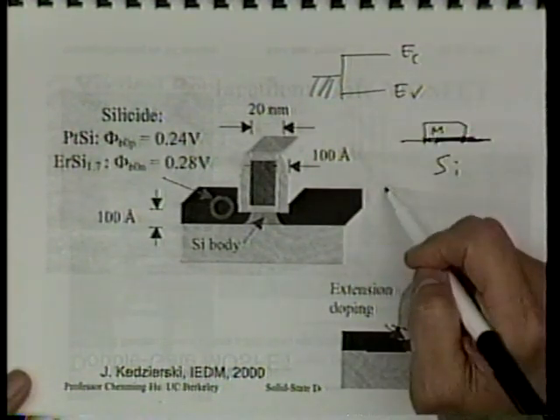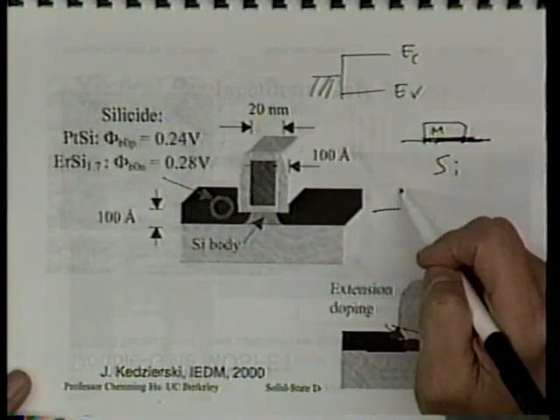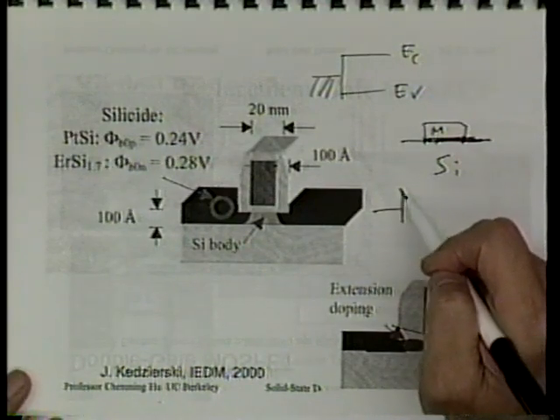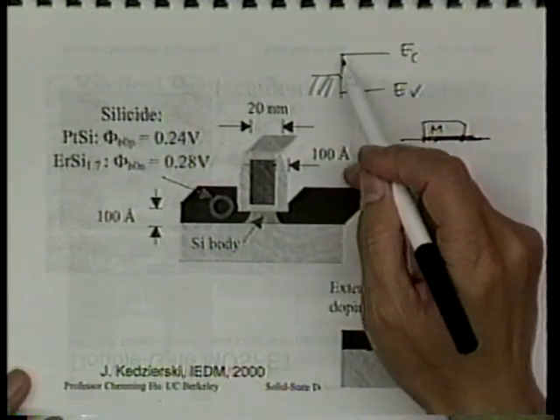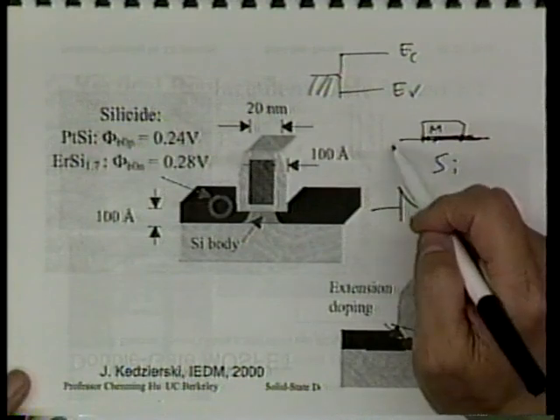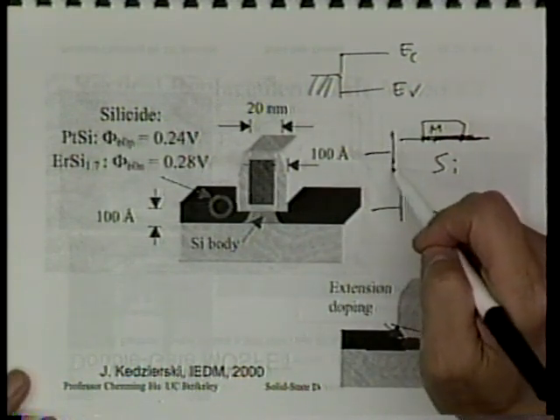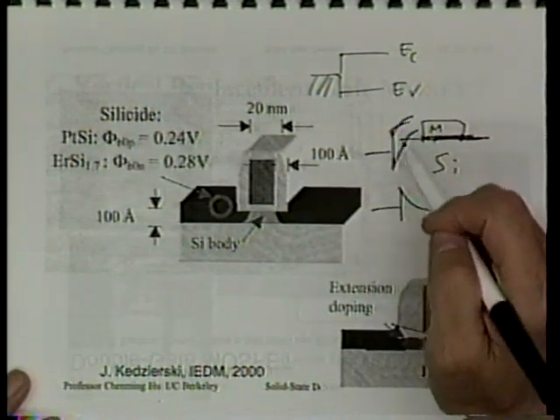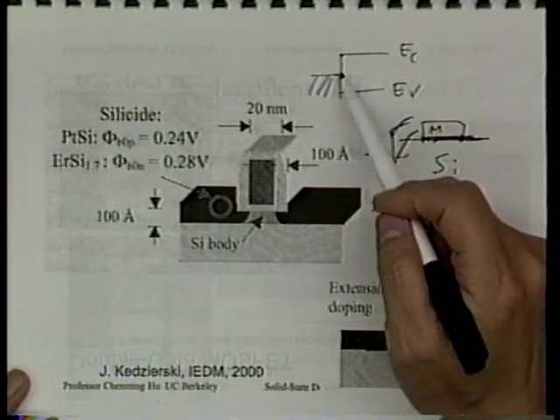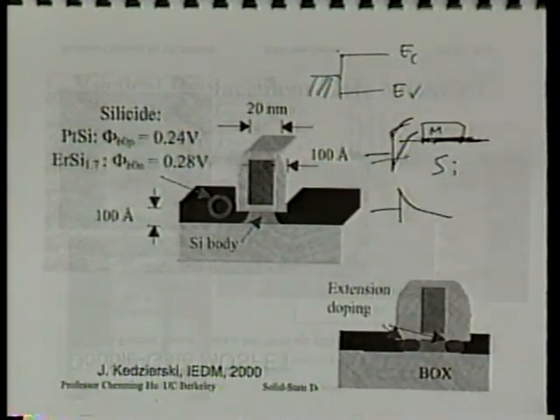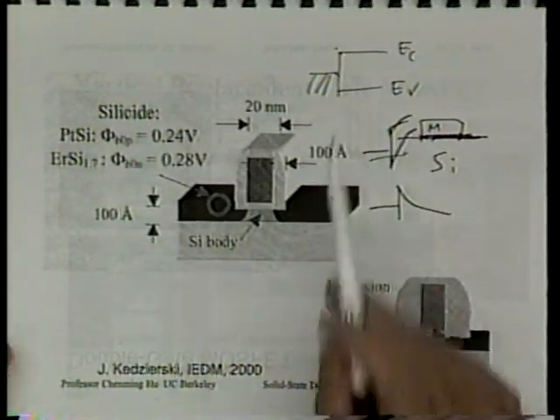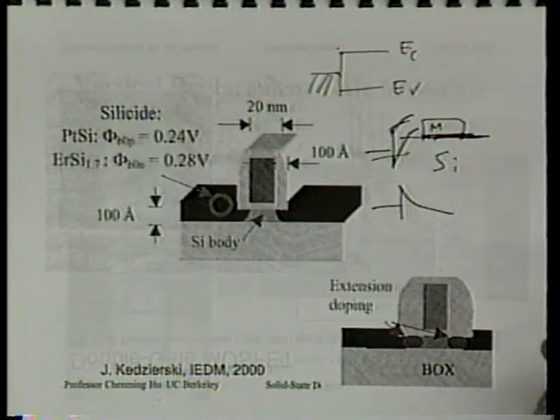In such a way, for electron conduction, the barrier is half of EG. You see that? That's the barrier. For hole conduction, the barrier is also half of EG. Is that right? For hole conduction, that's that barrier, right? That's the best you can do, right? And it turns out titanium silicide and cobalt silicide all happen to have about mid-gap work function, all right?